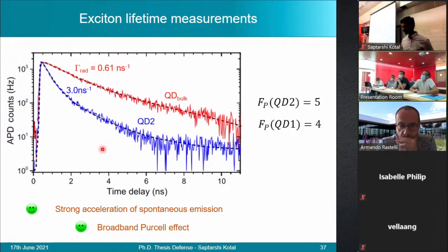So we are quite sure that we do not have any significant non-radiative processes, because if, let's assume there was some non-radiative process, then the radiative lifetime that we would measure would have to be much faster. And over the course of all the measurements that I've made, I would expect to find some values which would surpass the theoretically expected Purcell enhancement. Currently, out of the 10, we don't see any, but I've measured other dots as well, which we've not put in there, and we never go beyond the expected values. So yeah, we're quite sure that there's not much.